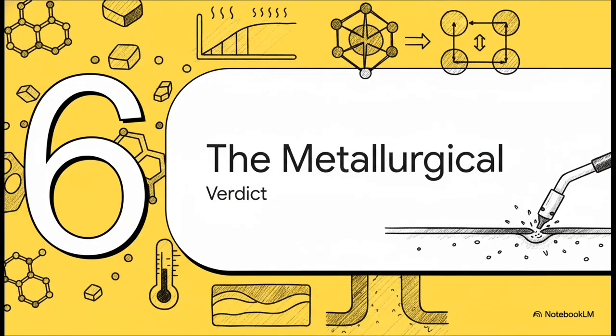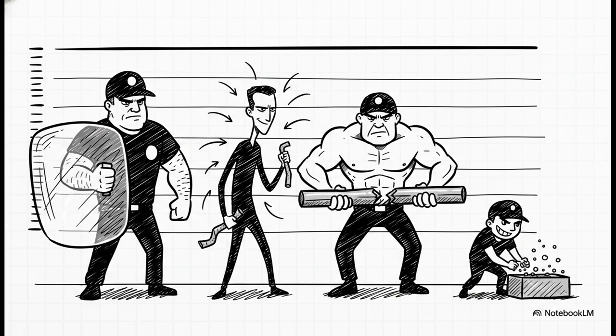So after looking at all the evidence, after running through all the suspects, what's the final verdict? Why is this stuff so hard to weld? Well, the case is pretty clear. We've got a whole lineup of culprits all working together. You've got that ceramic oxide shield you have to punch through, you've got the heat thief that warps the metal, you've got the high shrinkage that tries to crack the weld as it cools, and to top it all off, you've got the hydrogen saboteur creating weakness from the inside out.